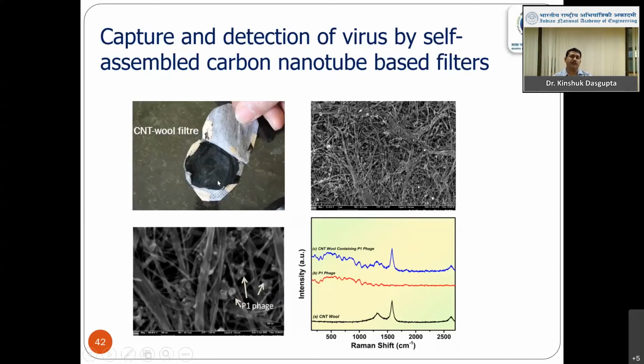also the flow, means, see, if we can make a filter or say mask using this material, it should not only capture the virus, but also it should allow the respiration to happen. So the pressure drop against this was not high. It was at par with the present N95 mask, but the capture of virus or say this particle was very, very efficient, more than 98%. And not only can you capture, you can characterize what this is, because this can be any other dust particle as well. By using Raman spectroscopy, you can identify what you have captured.